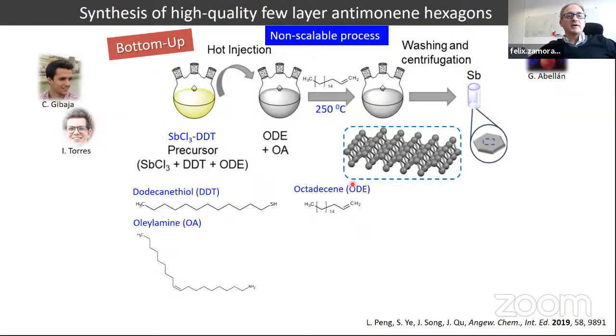And in order to solve that, we were just trying to develop an alternative route. And then we switch and change the approach. Instead of using this delamination top-down approach, we changed to a bottom-up approach. We do chemistry, and then we did this reaction between antimony trichloride and this complex with the dodecanethiol, this long molecule, this long thiol, and then we treat this solution with oleylamine, this long amine. This amine becomes a reducing agent of the antimony 3, and then doing this reaction under hot injection conditions.